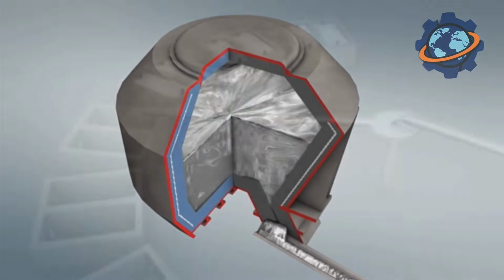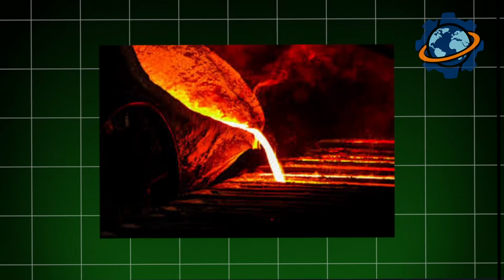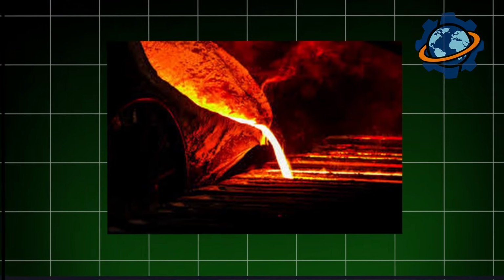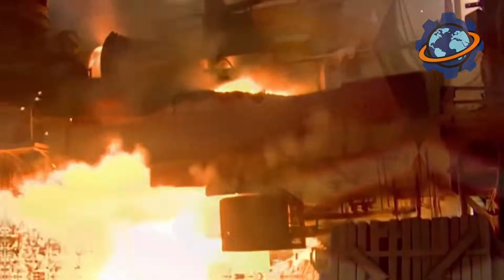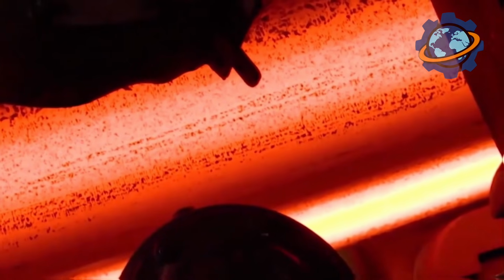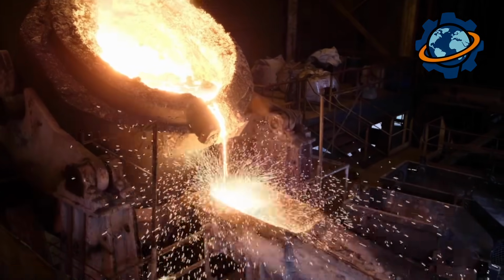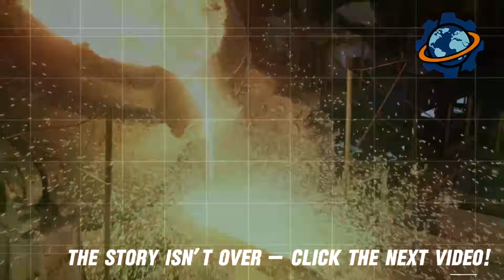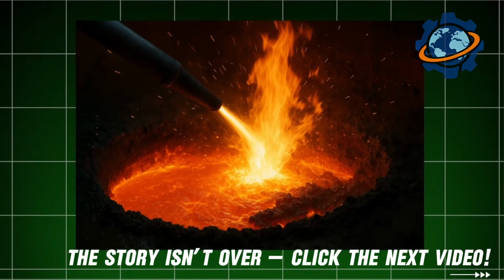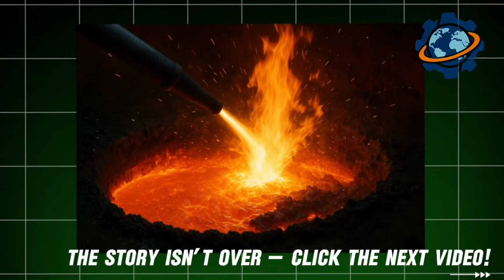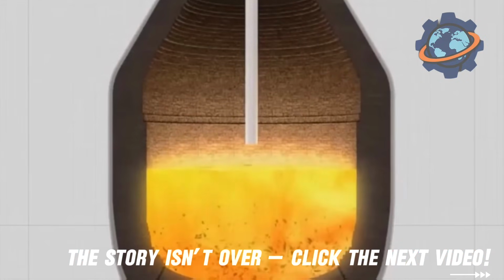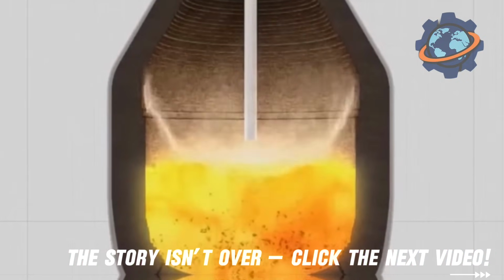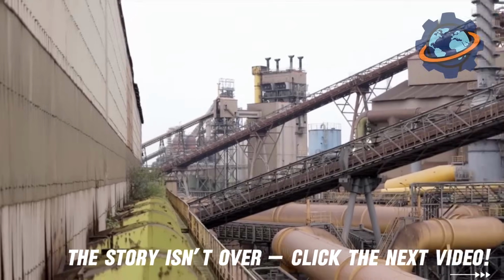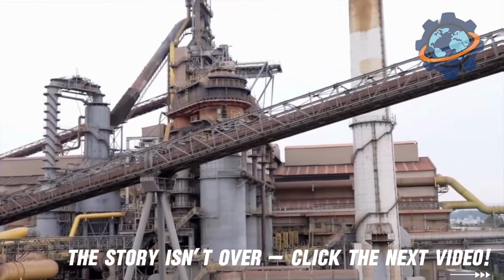The process looks impressive, like baptism of metal by fire. A steel beam 40 feet long is immersed in a bath of molten zinc. Temperature 840 degrees. The beam completely disappears in the silvery liquid. Chemical reaction begins instantly. Zinc reacts with iron on the steel surface, forming a layer of intermetallic compounds, a solid alloy of zinc and iron.